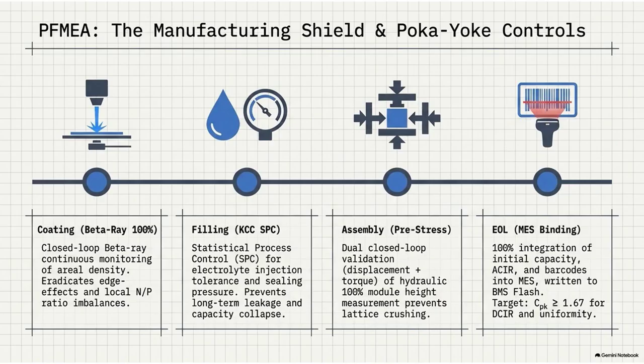Which is wild. The factory literally shoots nuclear radiation beta particles through the wet electrode foil as it passes down the production line at high speeds. The sensors measure the exact absorption rate of the beta radiation passing through the material. Because the absorption is directly proportional to the mass and density of the coating, the system can calculate the surface density of the active material down to the microgram in real time. So if the density deviates by even a fraction of a percent, the system feeds a closed-loop signal back to the coating die, adjusting the slurry flow pressure in milliseconds. It virtually eliminates the possibility of localized NP imbalances.